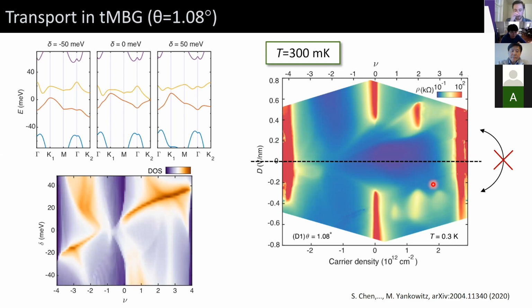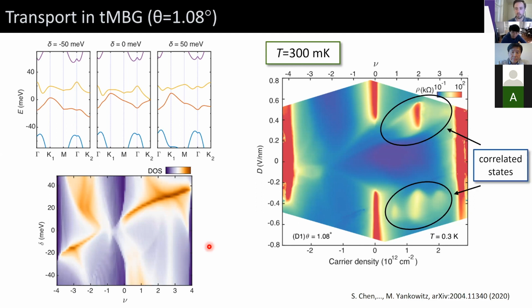So, again, a lot of this can be understood at a single particle level. If we just calculate the density of states, we see that there are a lot of similar features, in terms of Van Hove singularities that move throughout the valence band, and insulating states at neutrality and full filling. But I won't go into details about precisely how well these match. I want to instead focus on these correlated states, which are different between positive and negative sign of the displacement field.